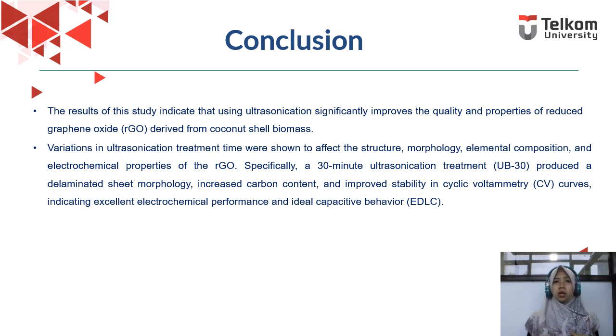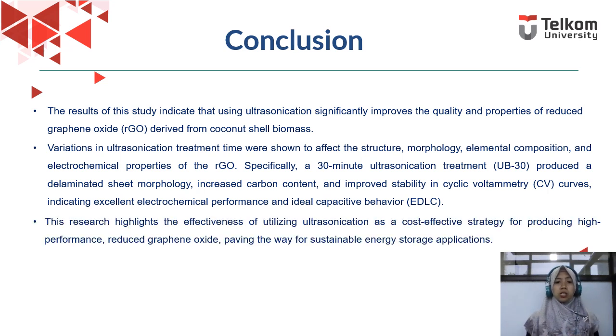Specifically, 30-minute ultrasonication treatment produced a delaminated sheet morphology, increased carbon content, and improved stability in the CV curve, indicating excellent electrochemical performance and ideal capacitive behavior. This research highlights the effectiveness of utilizing ultrasonication as a cost-effective strategy for producing high-performance reduced graphene oxide, paving the way for sustainable energy storage applications.